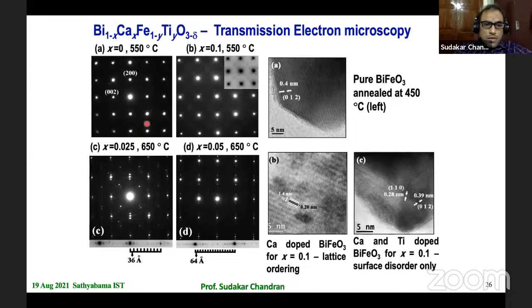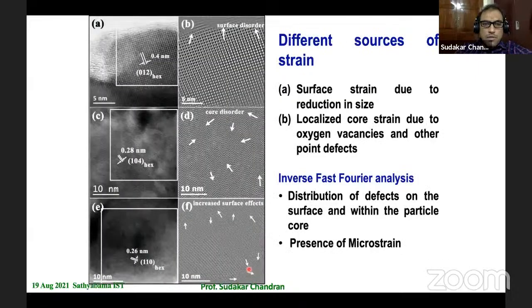Okay, so as you can see, the lots of dots, the ordered dots in these diffraction images, like the one shown, all indicate that the oxygen vacancy is in fact ordered in this structure. So here is one very interesting ordering that we found. It is almost like a 36 angstrom repeat order. In another case, we got 64 angstrom. Around 4 angstrom is the typical lattice size of BiFeO3. Now this becomes much larger because of the presence of oxygen vacancies. So oxygen vacancies, in fact, can be inferred from this kind of ordering that exists in these structures.